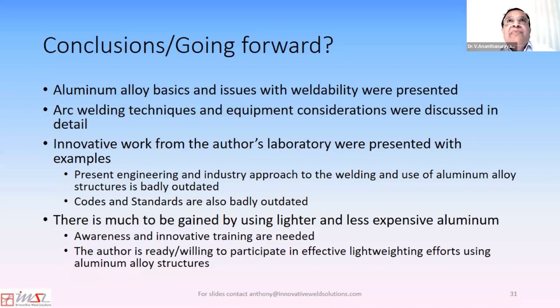Last, okay. Yeah. I am developing at this time for the US Navy mash seam welding of aluminum alloys. The 5000 series alloy that I mentioned becomes corrosion sensitive in the heat affected zone due to welding heat. I am developing welding for it using a mash seam welding process where I flood the weld area with water coolant during welding, so that the sensitization doesn't occur. And then the sensitization corrosion of the welded structure would not be an issue for the US Navy. Okay. I'm developing some of these.